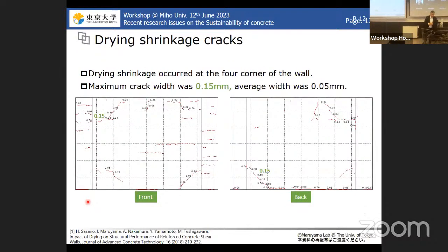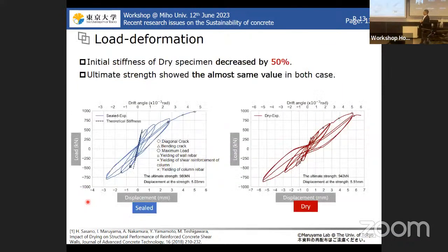This is what we observed after the drying of the concrete shear wall: we found very fine shrinkage cracking. The maximum crack width is just 0.15 millimeter, so it is not visible, and if we look at this shear wall, we generally believe that it is quite sound. And then this is our experimental result. This is the wet sample, and this one is the dry sample. And as you see, yeah, maybe I have to use this pointer.